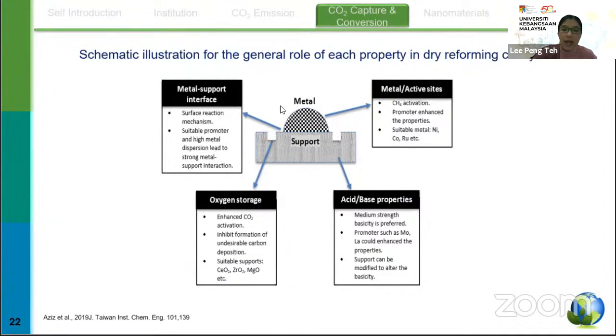The metal at this site is basically used for methane activation. Usually the suitable metals are nickel, cobalt, and also ruthenium, which are from groups 8 to 10 of the periodic table. And for the supports, it is good if we have very high oxygen storage capacity and also medium strength basicity. It will be good to enhance the DRM process.